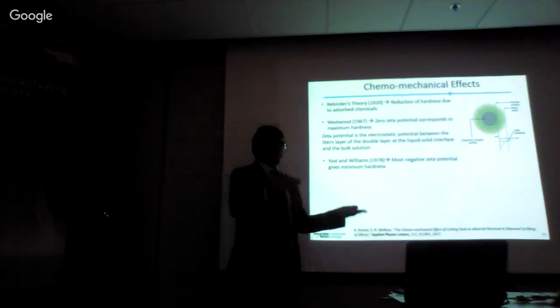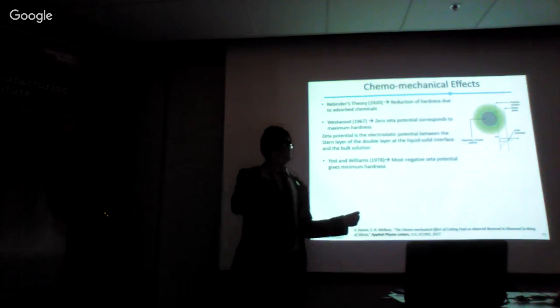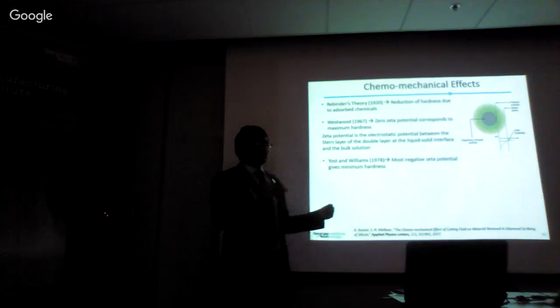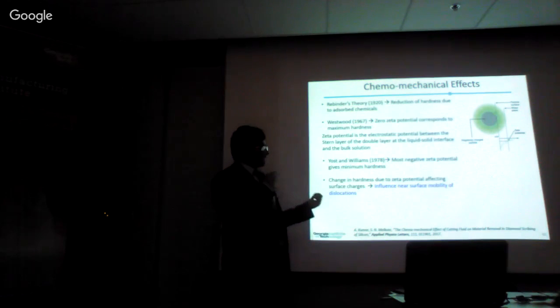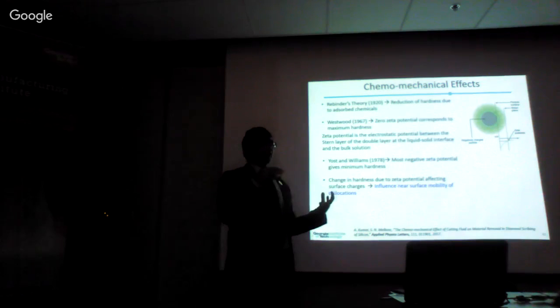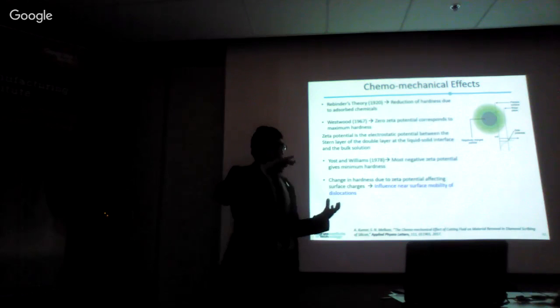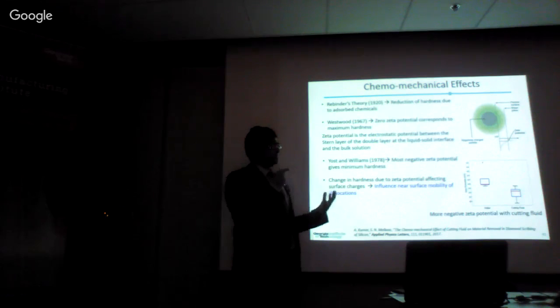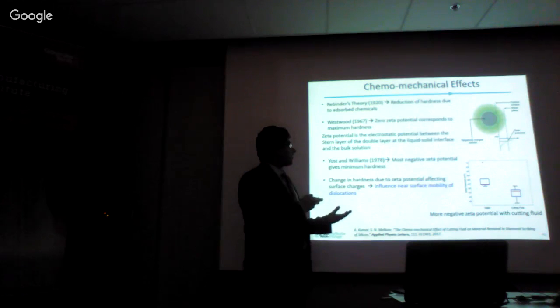Now, Yost and Williams found that more negative zeta potential gives even lower hardness, and the most negative zeta potential in the liquids they had investigated gave the minimum hardness. The reason hardness is reduced by zeta potential is that zeta potential changes the near-surface mobility of dislocations because of the surface charges created in electronic material like silicon, and that creates the reduction in hardness as